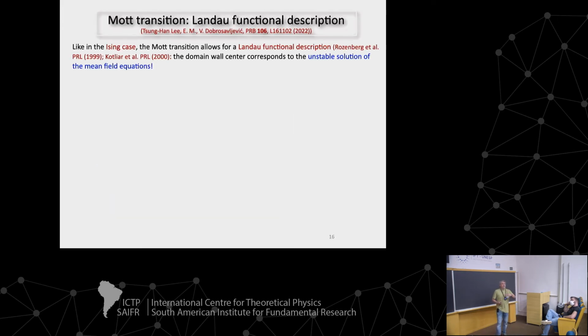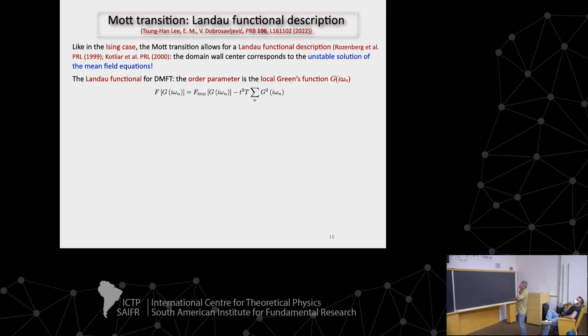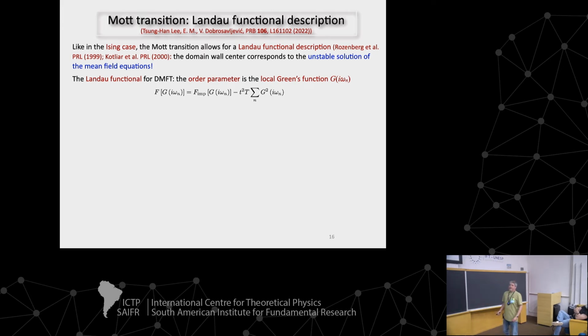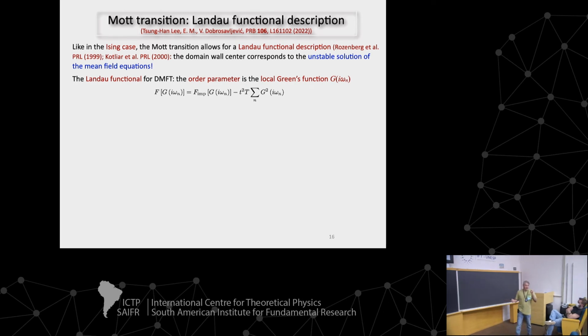So the Mott transition also has a Landau theory. You can write down a Landau theory within dynamical mean field theory for the transition. And what I'm going to show is that the domain wall is the unstable solution. So this is the part where it becomes very technical. I cannot explain it here, but the actual order parameter, the full order parameter of the dynamical mean field theory, is a function, not a number. It can be the Green's function. It can be the self-energy. I took the Green's function here. You can write a Landau functional for that function, G of iω. And then if you find the minima, you get the two phases. If you find the maximum, you have the center of the domain wall.